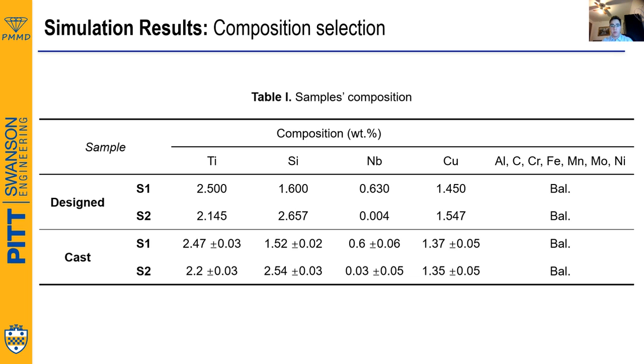For the majority of the elements, they are pretty much the same, even including for copper. You see there's only a small difference. But the main difference between the two samples, S1 and S2, is the titanium silicon ratio as well as the niobium content. The niobium in S1 is much higher than in S2.